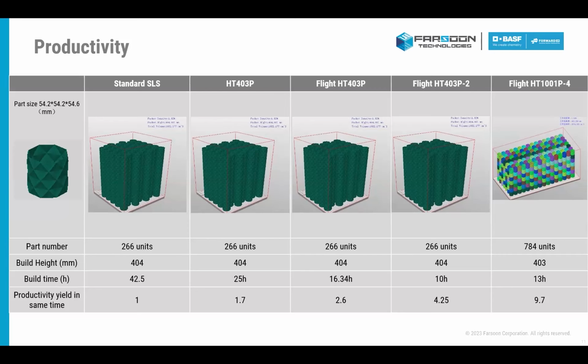Moving to our dual laser flight system, we can see that we can cut down the build time even further to a mere 10 hours, giving us almost 4.5 times the productivity yield. It's 266 parts in 10 hours compared to 42 hours in a standard SLS system. And then finally, to round out our system comparison, I want to take a look at our quad laser 1001P. As we can see, we're able to complete a 13-hour build and produce 784 parts. It's 3 times as many parts in our mid-sized platforms completed in less than a day.